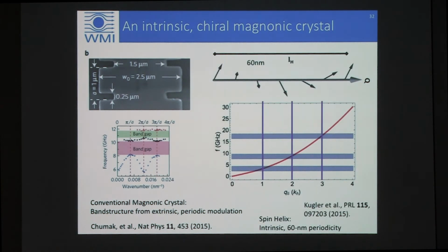Now, the interesting thing about the case of the copper oxyselenide, or of any spiral magnetic material, is that it has an intrinsic length scale, or an intrinsic periodicity set by this helix length, the 60 nanometer. So it's basically like a magnetic crystal with a lattice constant of 60 nanometer, which is challenging, not impossible, but challenging to fabricate with nanolithography. But the quality of that crystal, right, so this works over millimeter scales of the samples, right? It was 8 millimeters long. They have almost a perfect periodicity. I'd say that's impossible to do with nanolithography, right? Getting that resolution on an 8 millimeter length scale.